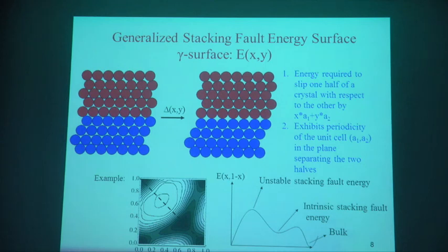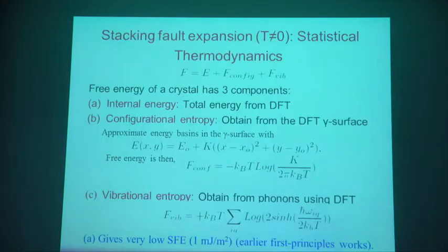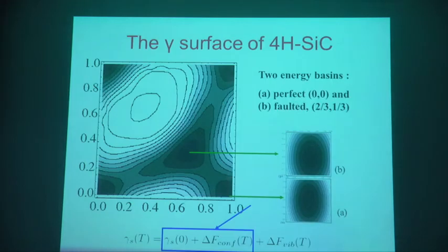It happens as a function of temperature. At low temperatures, you don't have these faults. So that's where we use what I told you in the last slide. Basically, we calculated internal energy using DFT, configurational entropy using a simple formula, and vibrational free energy using the quasi-harmonic approach. And that gives us the stacking fault free energy.